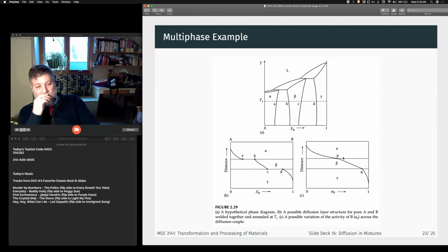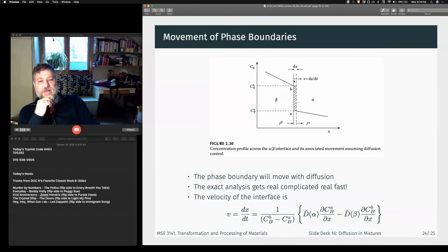And we can look at the activity, or our chemical potential, and what we see is across our sample, our chemical potential or our activity has to be continuous. Remember that chemical potential is the driving force for diffusion, not the composition itself. So what we end up with is a profile where we have a continuous activity or chemical potential curve. We always have to maintain equilibrium at this interface, and these phase boundaries themselves are going to move with diffusion.